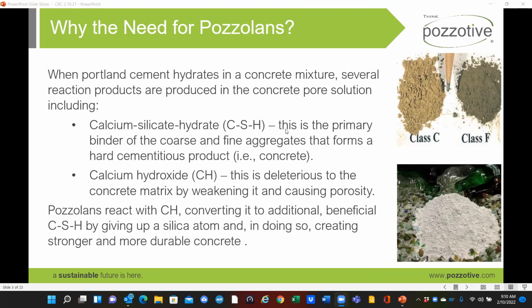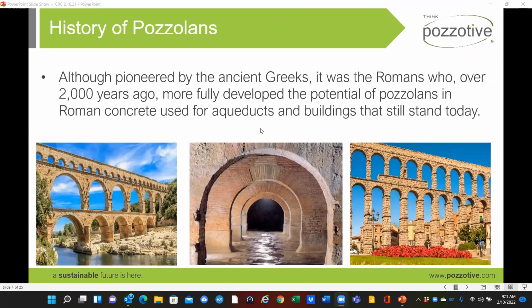Glass, like fly ash and slag, that photograph above is a photograph of fly ash, another pozzolan, have a common feature. They all have a high silica content. As a pozzolan, glass gives up its silica to the calcium hydroxide, creating basically more calcium silicate hydrate. So that's the magic that occurs. That's why it's not just an inert addition to concrete. It's helpful in making a stronger, better performing concrete. So I think it's important for people to understand its significant benefits to concrete in our country. Pozzolans have been used going back to the Greeks and Romans over 2,000 years. Those of you who travel through Europe have seen these structures still standing as a result of the good use of pozzolans back then.